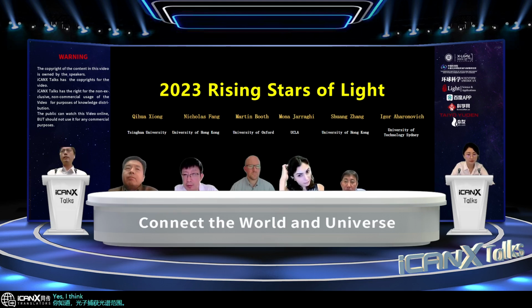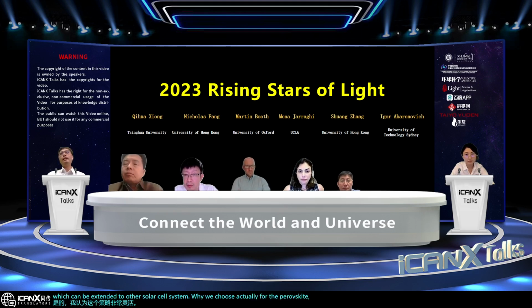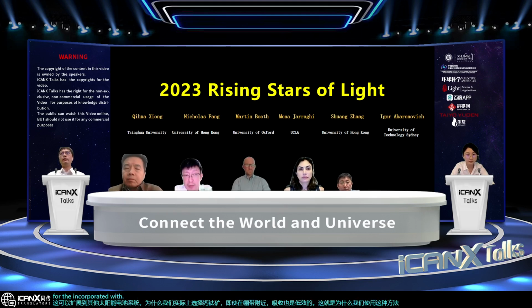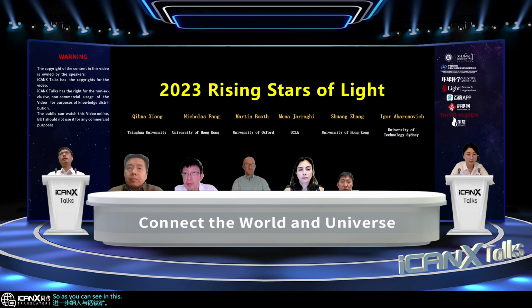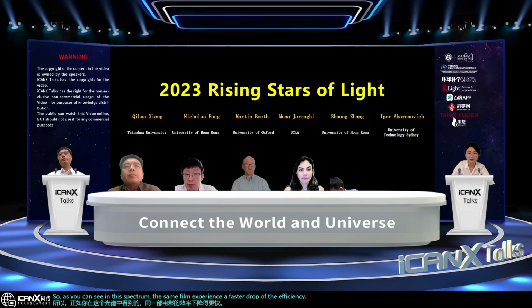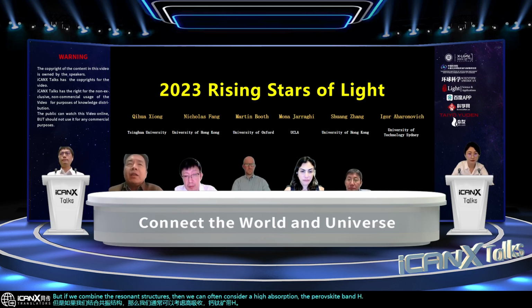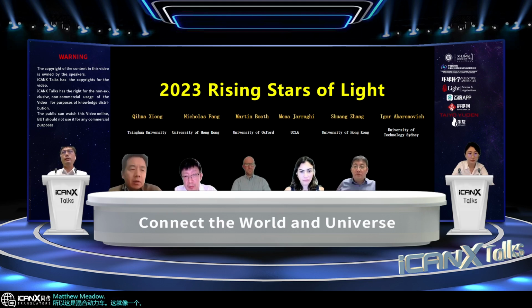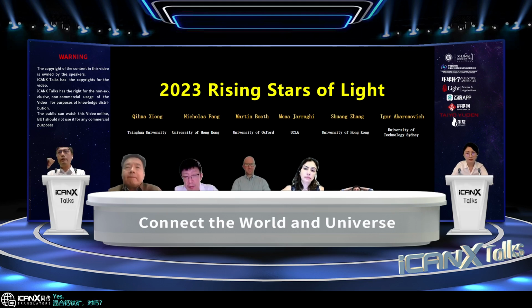Yes, I think this strategy is very flexible, and can be extended to other solar cell systems. Why we chose the perovskite is that, even near the band edge, the absorption is inefficient. That's why we use this method to further incorporate with perovskites. As you can see in the EQE spectrum, the thin film experiences a faster drop of the efficiency. But if we combine the resonant structures, then we can obtain considerably high absorption near the perovskite band edge. Okay, so this is a hybrid perovskite, like a methylammonium type? Yes, hybrid perovskite. Okay, I see. Thank you.